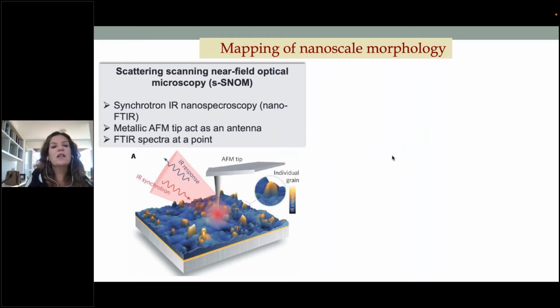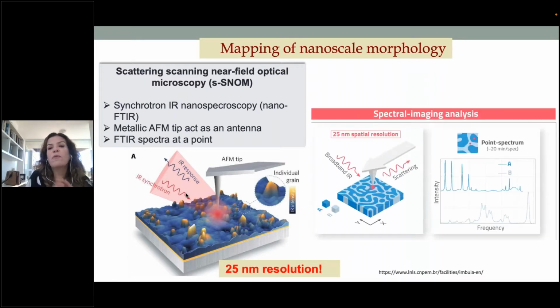So here we combine AFM. The AFM acts as a kind of antenna. And we combine the AFM with the infrared from the synchrotron with a resolution of 25 nanometers. So using this technique, you have basically two results that you can obtain. You can obtain what we call a broadband image of the film, and we can also get what we call a point spectrum. I'm going to show these two results.